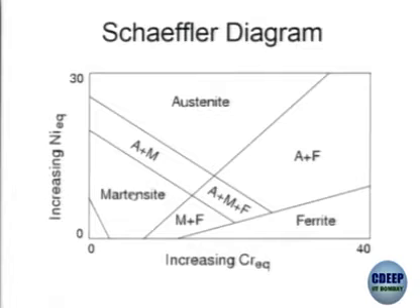Now you have understood this. This plot is nothing but total nickel equivalent, that is total austenitic stabilizing elements, and total ferritic stabilizing elements. Now you just see in the beginning, if I have less nickel and high chromium, it starts with the ferritic, but as I start increasing the nickel concentration, the structure can be martensitic or ferritic. As the chromium concentration increases, you stabilize mostly the ferrite. But if you start increasing nickel, then you find a very clear change. You start with the martensitic kind of thing, then you have martensitic plus ferritic, then at some stage you become, okay, you understand like this.